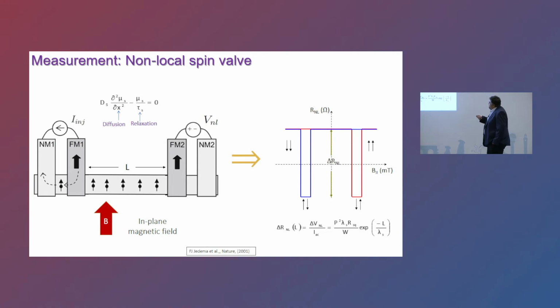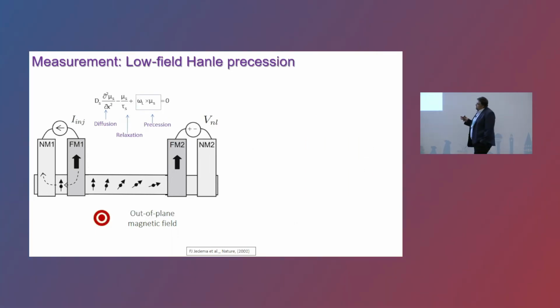This is a very typical spin valve measurement that you will get if you measure any material under this non-local spin valve geometry. I'm showing it because later I will show you that these kinds of measurements give a different response for black phosphorus, and I will try to explain why they are different. The second measurement we are doing is called Hanle spin precession measurement.